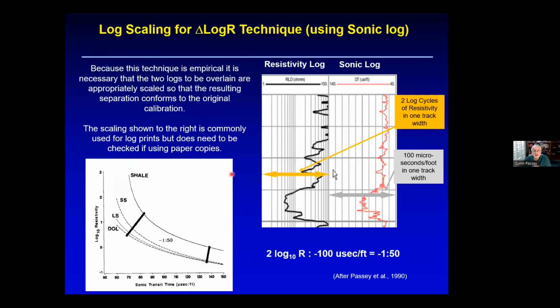The scaling that was used is very simple. The technique was developed to be used at well site when they had the old film recorders. And so you'd be at well site, you'd plot off the resistivity, and then you had the sonic and the scaling that we used, and you can read about it in the appendix of our 1990 paper, but we just used an approximate scaling of a -1 to 50 as the range where these things will kind of track. When you're very tight on the left side here, it will not track. You'll have to do another kind of scaling. And if you're very undercompacted, it also will not track exactly. But again, go to the appendix of this paper to see more detail.